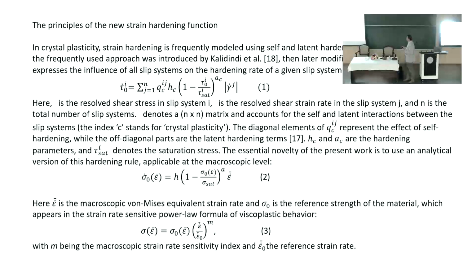There's a dot, important. Because there is slip in one slip system, there will be an increase of the resistance to slip, or dislocations, in another slip system — in all of them within the same crystal. So here this is index J, and here is index I.